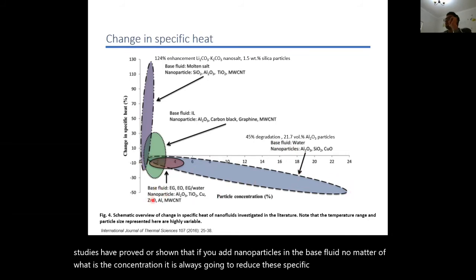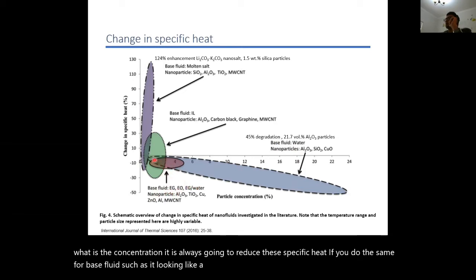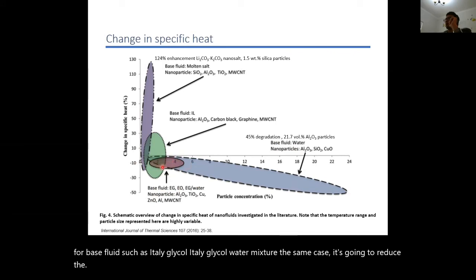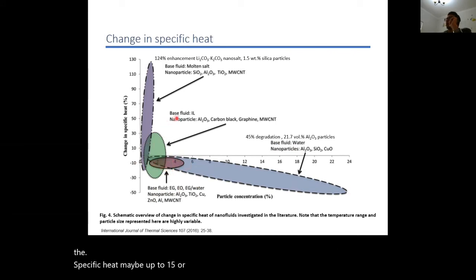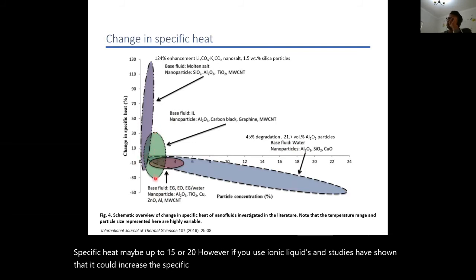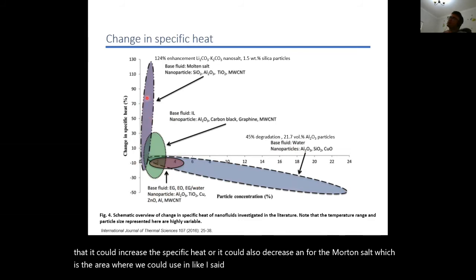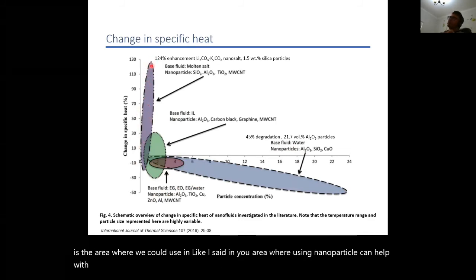If you do the same for base fluids such as ethylene glycol water mixture, it's the same case: it's going to reduce the specific heat, maybe up to 15 or 20%. However, if you use ionic liquids, studies have shown that it could increase the specific heat, or it could also decrease. And for the molten salt, which is a new area where using nanoparticles can help with better properties, such as the specific heat, it will also result in improving your storage.